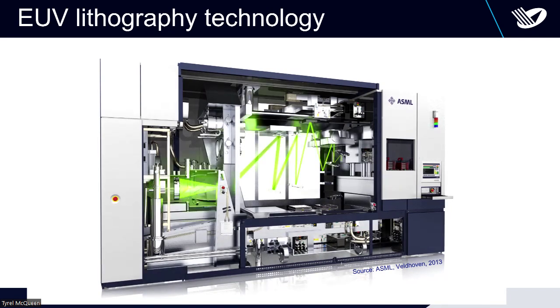So this is basically how that works. You have these droplets here that are fired by tin, the tin droplets that are fired on by a CO2 laser. The light is caught and then directed with a few mirrors onto a target, and then onto the wafer where the wafer is being printed.